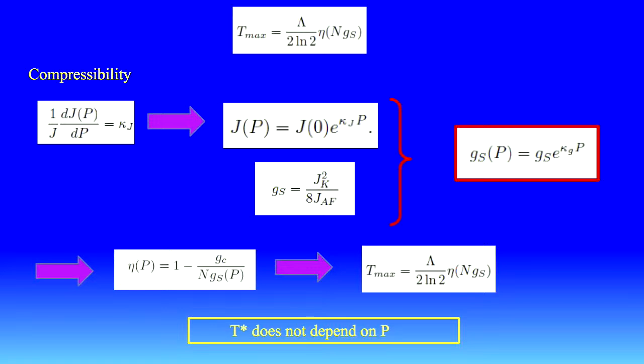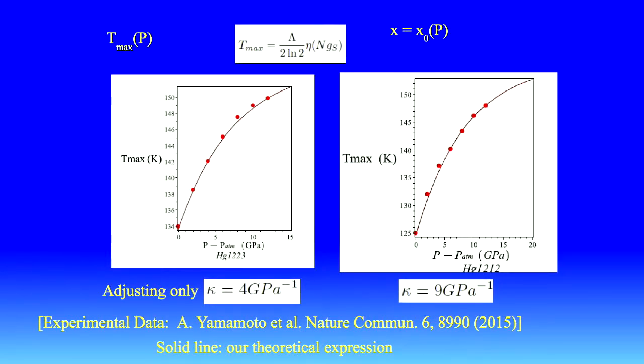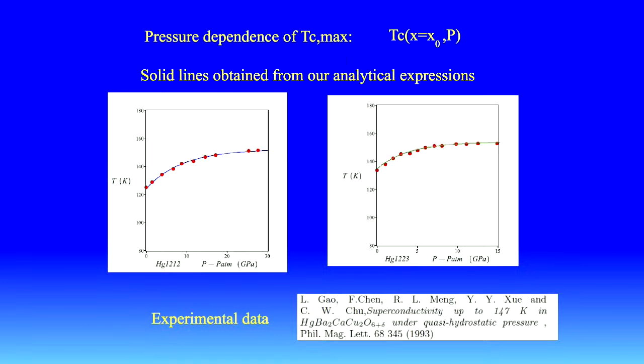So, conclusion: pseudo gap does not depend on pressure. And TC, look at the result, for X corresponding to the optimal doping. And these are the adjusted parameters. This is the same result for these different materials.